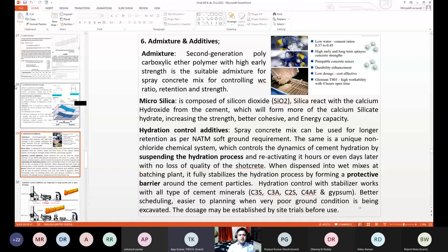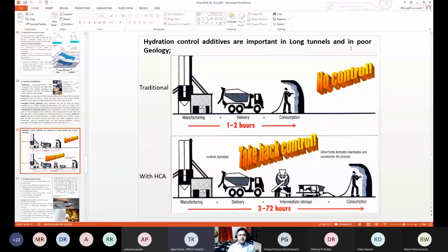Now, hydration control additives are important in long tunnels and in poor geology. Traditionally, the batching plant is near and you have to spray immediately, within 1 to 2 hours. But with the HCA, you can go up to 3 to 72 hours. You can make the mix at the batching plant and put the hydration control additive in at site as and when required. Because in NATM soft ground condition, the shotcrete should be prepared and readily available at site while excavating the face. In case of any failure or problem, you can immediately spray the shotcrete over the ground. So this is the advantage of HCA, hydration control additives.